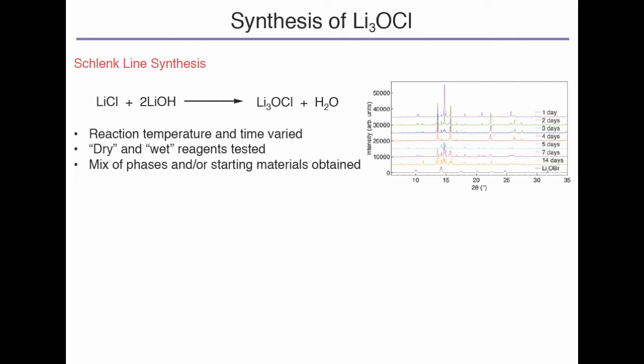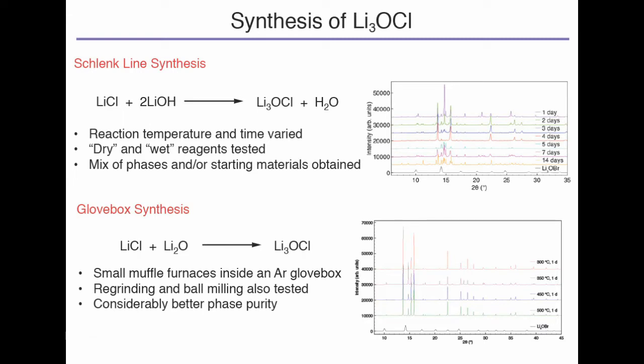So we decided to abandon that synthetic approach and do something different. We decided to take some small furnaces, so heating devices, inside a glove box, which is an inert atmosphere, and do the entire reaction inside the glove box. This time, using slightly different starting reagents, lithium chloride and lithium oxide, but the principle's the same. You heat it up and the Li3OCl should just crystallize out.